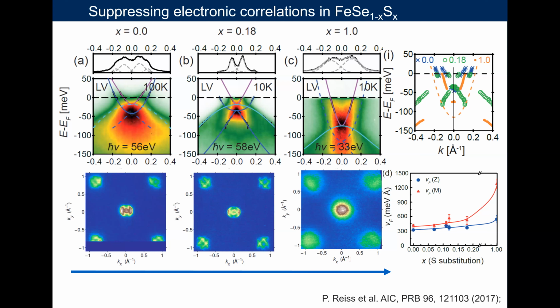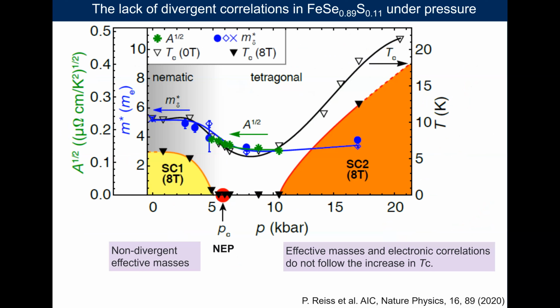Here, we've done similar experiments, again with pressure, to probe the behavior, to be sure that this is not just a fluke, because we have different types of samples. Here we have a single sample in a pressure cell, and we follow the behavior of the same band, the delta band, and the blue points are what happens to the effective masses. They are quite strong, large, about 5 inside the nematic phase, and then they decrease. And you can see that there's no divergent behavior at the nematic endpoint.